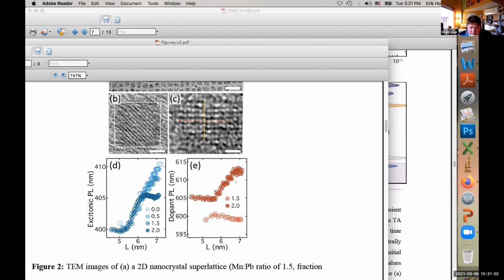Right? Again, it needs more thinking, but if it were a presentation to a big audience, I would put nearby the figure from a textbook showing the formation of bands, where one level, two levels, and then multiple levels converge to a continuous band. So if you go to higher concentration of manganese, the band edge becomes lower and lower. Yes, because here is one, here is several. Energy levels always repel each other, and then the lowest one in the band will be lower than the isolated one.